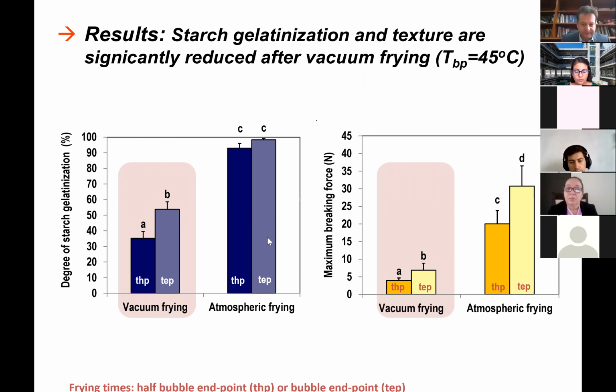So here we have what happens to the vacuum fried samples that were processed at the lower pressure, and that means at the lower temperature. So we were somehow restricting, importantly, the degree of starch gelatinization. So this is what happens through half of the process and at the end of the process. And we were able really to reduce starch gelatinization significantly compared to atmospheric frying, where nearly 100% of the starch gelatinized.